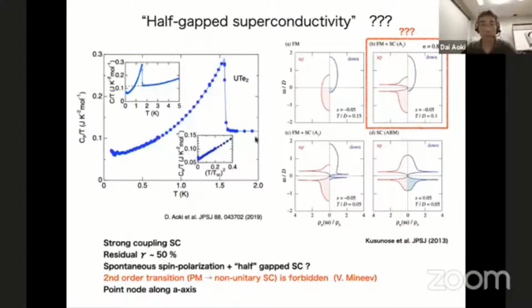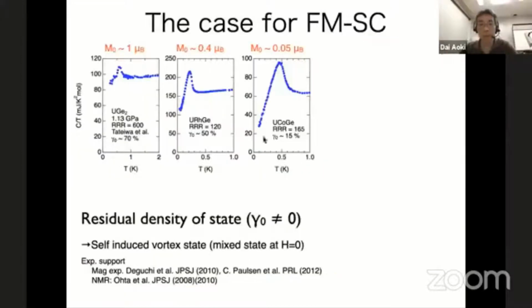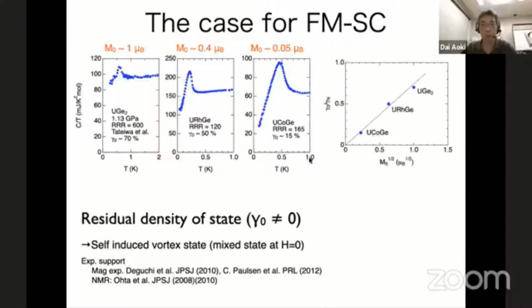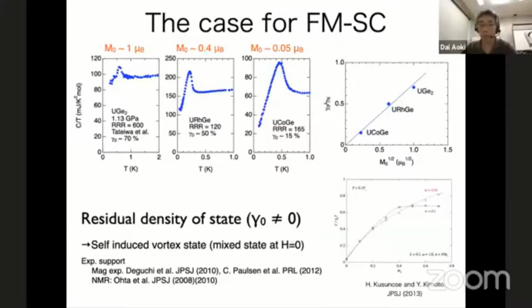So coming back to the ferromagnetic superconductor, we learned already that the residual density of states is related to the ordered moment. Here is 1 μB, 0.4, and 0.05 μB. And there is a good relation between residual density of states and ordered moment. But uranium ditelluride is a paramagnet, so we can expect zero residual density of states. So the question is why such a large residual density of states appears in this material.